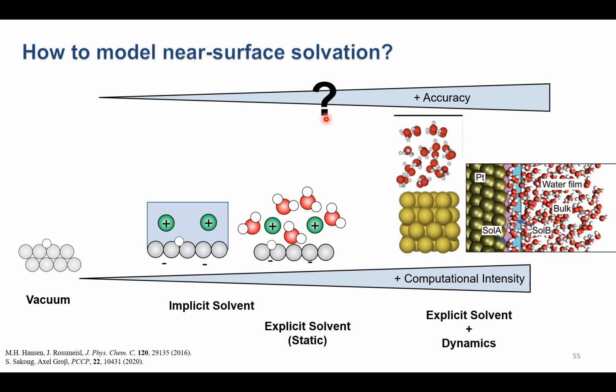Instead of trying to capture effects on electrocatalysis or trying to study electrocatalysis directly, we need to also devote some time into studying what is the effect of water near a surface, what is the behavior of water near a surface, and what is the best way, most accurate way to model that for a given electrode, a given electrolyte, a given set of conditions. I'll just mention briefly, I think we can model hydrogen adsorption on platinum in vacuum and can match experiment very well when we don't see competition from water adsorption or water decomposition. And so we can then totally ignore solvent near the surface and be very accurate with a model in vacuum.